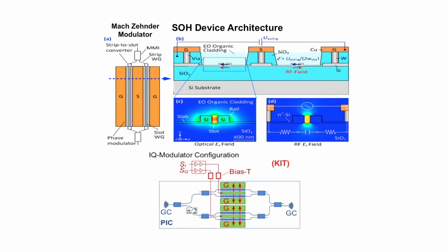Initially, we pursued silicon organic hybrid device architecture such as shown here. So what we do is we take a silicon waveguide, which is already with dimensions on the order of a few hundred nanometers rather than micron dimensions of a lithium niobate modulator. And we cut slots in this. And these slots can be as small as roughly 25 nanometers. You fill the slots with organic electro-optic materials. I show you the poling fields denoted in black, and the RF drive fields. And so you, in this configuration, produce a push-pull modulator.